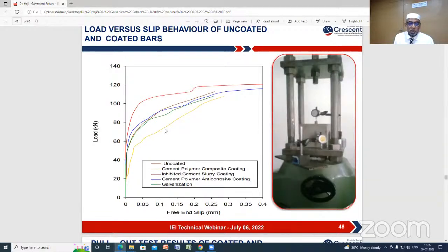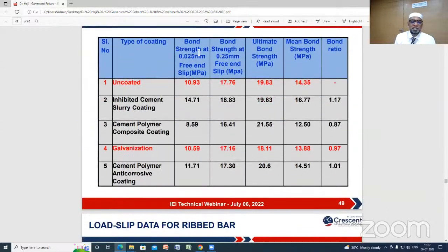These are our lab results. You can see that the brown color curve is the uncoated rebar and the green color curve is the galvanized rebar. The brown and green curves go almost the same way. It clearly indicates that because of the galvanization process, there is no disturbance to the bond strength development between steel and concrete. The bond strength at 0.025 mm free end slip is 10.93 MPa for the uncoated and a similar value for galvanized. Again, 17.76 and 17.16, so almost similar bond strength values for galvanized rebar as compared to uncoated steel rebars.